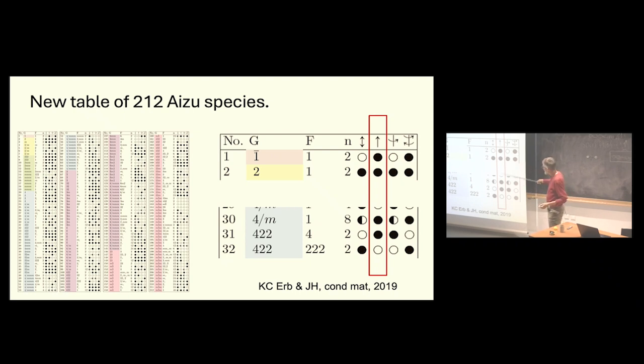So you can see immediately how many of these possible 212 species are ferroelectric and which are not. What I found very interesting, which we didn't understand in 2016 when we first published the paper with Vašek Janovec, is that actually the neutral bidirector tells us whether it's a ferroelastic material.